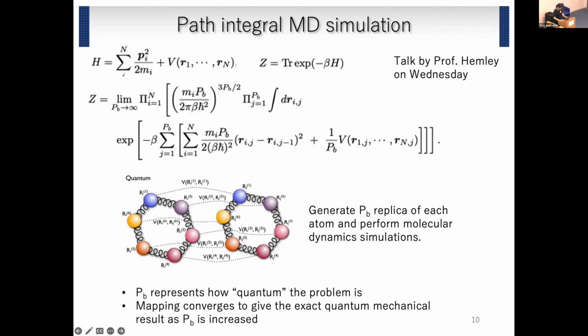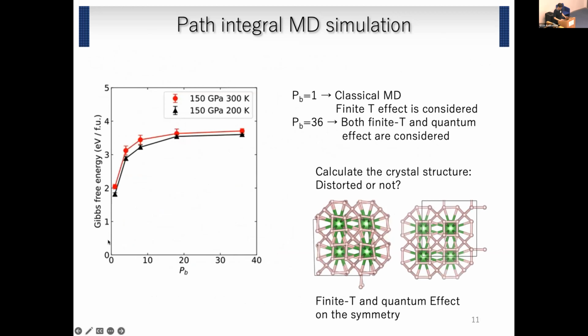And so this is the plot of free energy as a function of P. P equal to 1 corresponds to the classical molecular dynamics. By doing this calculation, we can think about the effect of finite temperature. And we see that if P is as large as 36, then the result is almost converged. So hereafter, I'm going to show the results of P equal to 36.